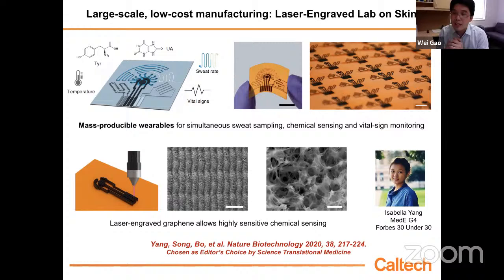Think about that. Typically, people do electrochemical sensing. If you want to improve the sensitivity, you need to immobilize nanomaterials. Most people use drop casting, immobilizing the electrodes one by one. In this case, even if the electrode has good performance, you don't have very good reproducibility, right? Using this platform, we can mass produce sensors at a larger scale and still with very high performance. The lead author, Isabella, recently received the 2021 Forbes 30 under 30 because of this work.